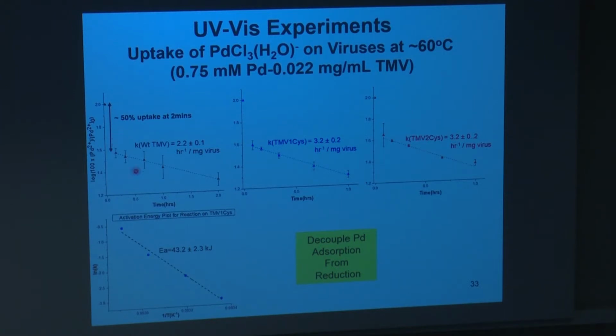drop in the palladium concentration within about 2 minutes. That probably indicated that some type of absorption, palladium absorbing onto the surface of the TMV, because in the UV-Vis experiment, we have to filter out the palladium. And you have to filter out the TMV. And if we're filtering out the TMV, then any palladium that's absorbed onto the TMV will be filtered out as well, even before it starts to reduce.